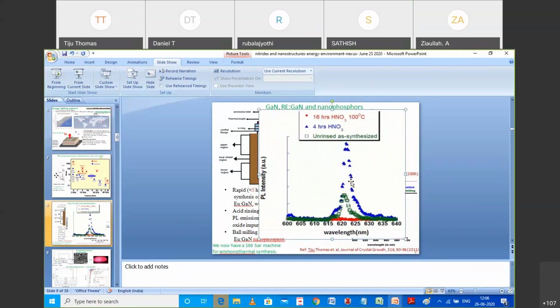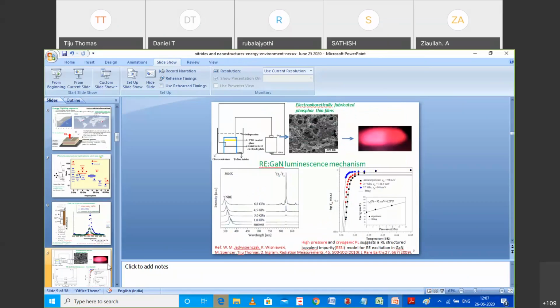Now, the good news is for the blue LEDs that are coming in the market, you could put this on top of that. So you would be able to excite this material using blue. You would be getting blue plus red. And if you invented a material for green, then you would get red, blue, and green. And then you would be making white LEDs here in India by using our own native technology. And that would be a very nice thing. And as I said, there is a lot of prospect for this.